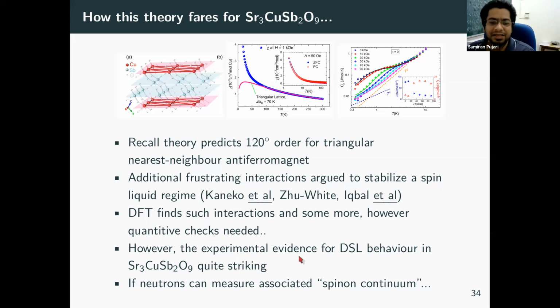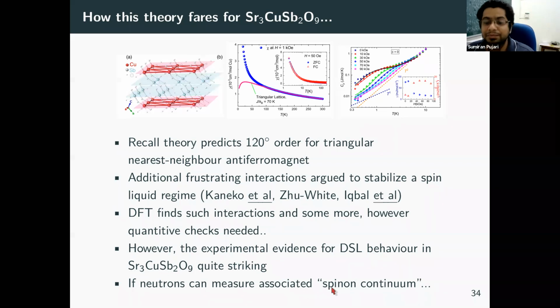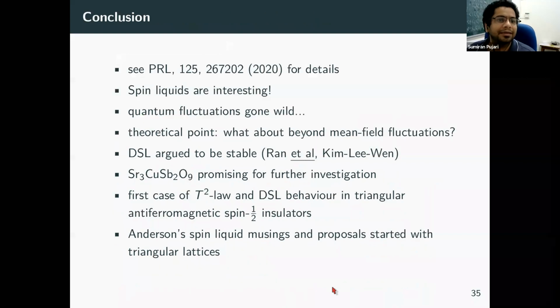However, the DSL behavior in this material is quite striking, and so further investigation is probably warranted. And for the experts, if neutrons can measure the spinon continuum in this material in a single crystal, that will be quite nice. So this brings me to my conclusion. I went over time a little bit.